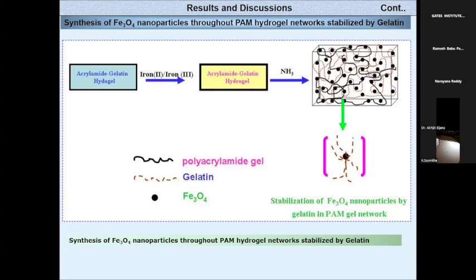So what will happen during that time? This hydrogel will absorb the water. It will not only absorb the water, it will also absorb the iron ions that are in the solution. It will absorb the iron ions into the hydrogel. Once it is done, this acrylamide hydrogel which has absorbed the ions is in a swollen state.